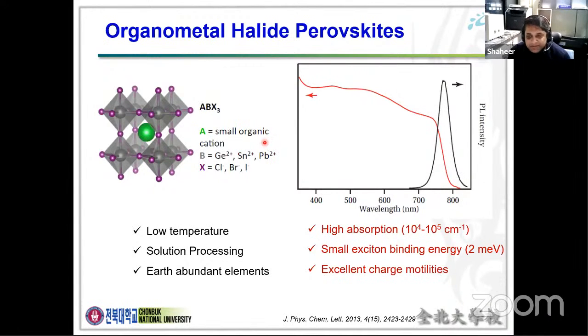Maybe most of you are aware of this, but I will briefly explain why the perovskite material is suitable for the solar cell. The perovskite materials follow the formula ABX3. A and B are two cations; among them, one is the big cation and the other is the smaller cation, and X is the halide. Usually A is an organic cation; the commercial or reference one is the methylammonium cation, B is lead, and X is iodide. Whenever we fabricate a perovskite solar cell, we always compare our device performance with the reference perovskite material, that is methylammonium lead iodide.